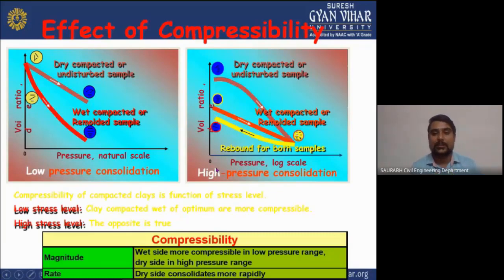Now we can see here this is the effect of compressibility due to the pressure which we use during the compaction. Wet side is more compressible in the low pressure range, dry side in the high pressure range. And what will be the rate? Dry side consolidation will be more rapid. As you can see, these are the two graphs which are showing the relation between pressure on natural scale and void ratio. And this is for the low pressure consolidation, and this one is for the high pressure consolidation.